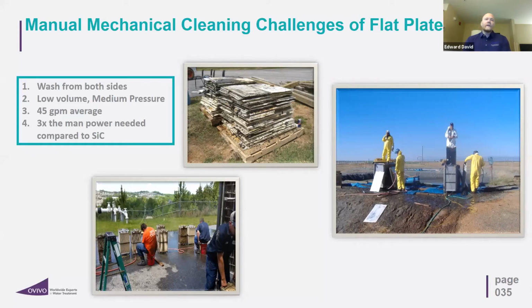But what you also see very closely on the left, you have people sitting down, holding hoses, washing down the membranes. You have to wash them from both sides. And you typically have to dismantle them to get to them. And unfortunately, once you start doing that, you have the tendency of some human error and some damage. So we would typically see around 5 and maybe up to 10% of damage just from tearing things apart and putting them back together. One thing to note is the amount of water: it takes at least 45 GPM to be effective, because about 12 to 15 gallons per hose, 2 to 3 people, sometimes more. Pulling people together and attacking this is not anything that happens quickly. The one to the right took us a week, only 9 units. The one to the left took us 2 weeks, but it was a much larger plant.